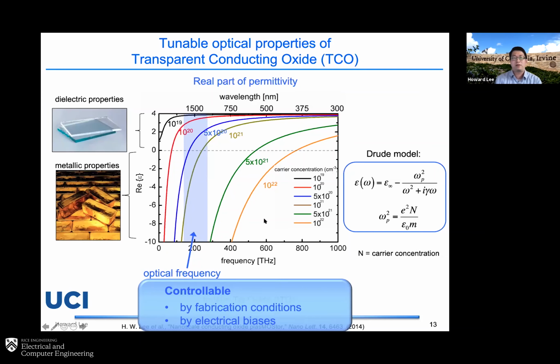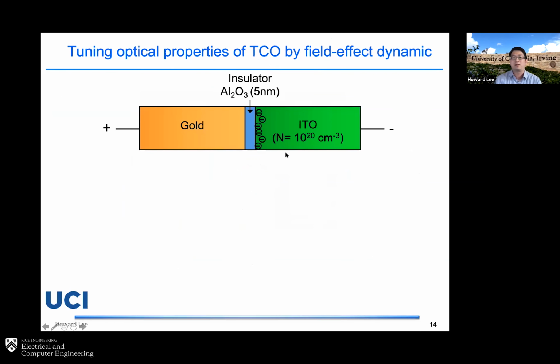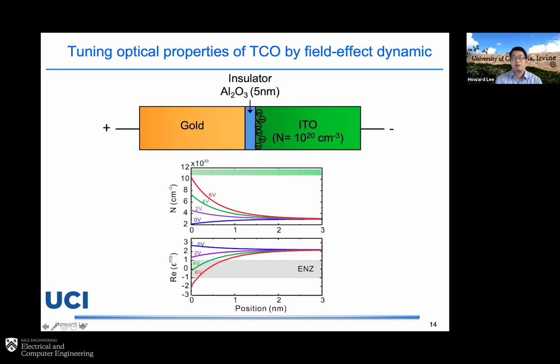To electrically tune that, you can imagine constructing a structure like a MOS transistor. You have a metal, insulator and semiconductor. Using the so-called field effect by applying an electrical voltage, because you have an insulator here, your electrons will accumulate. As a result, you have an increase in the electron density, and you can change the material property at this interface here. To show you this, I'm plotting the electron distribution of the ITO material for different voltages.